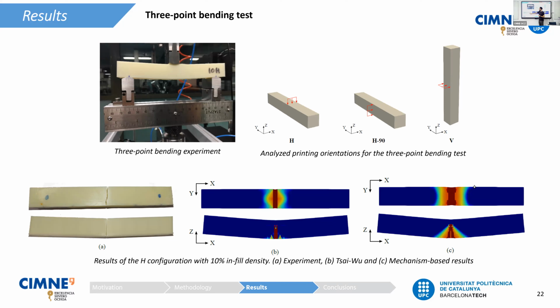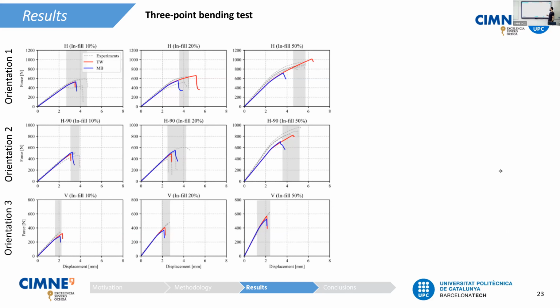And we compared the experimental results with the computational results using the Tsai-Wu damage criterion and with the computational results using the mechanism-based damage criterion. These are the contour fields of the damage variable, and we can see that in this simple case where only normal stresses appear, there's only one failure mechanism possible that appears always in the middle. And of course, this phenomenon is properly captured with both Tsai-Wu and mechanism-based criterion. If we take a look at the force displacement curves, again, we can see that the difference between the experimental results and the computational results is low for both Tsai-Wu and mechanism-based damage criterion, except for these 2 cases over here.